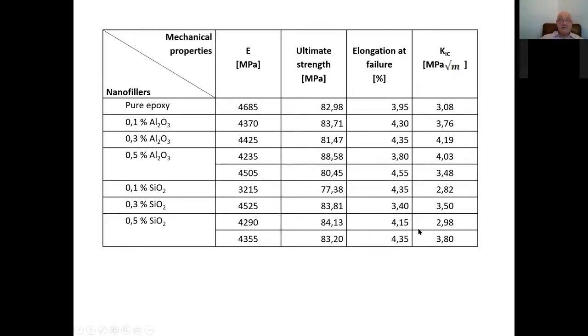So why does this happen? We're going to see immediately. From the point of view of mode one stress intensity factor, we got some values which were peculiar. Now I have to mention here that the crack is made by striking with a blade, and in some cases, as the material is fragile, epoxy is essentially fragile, the specimen broke.